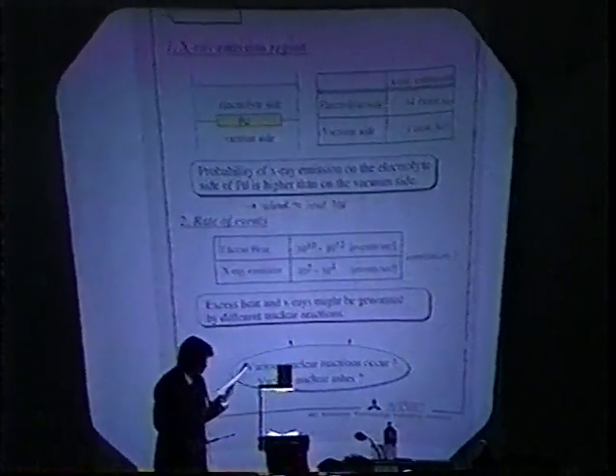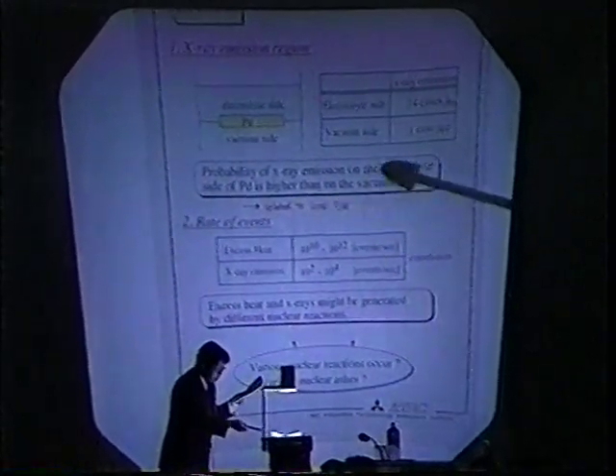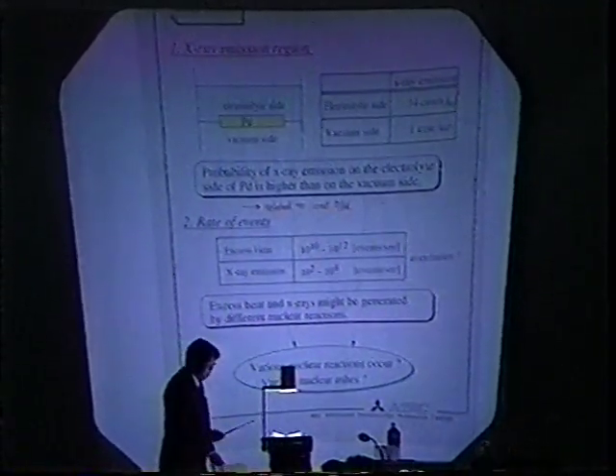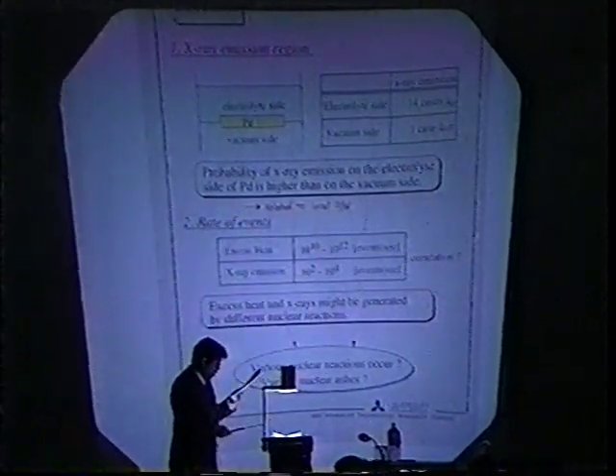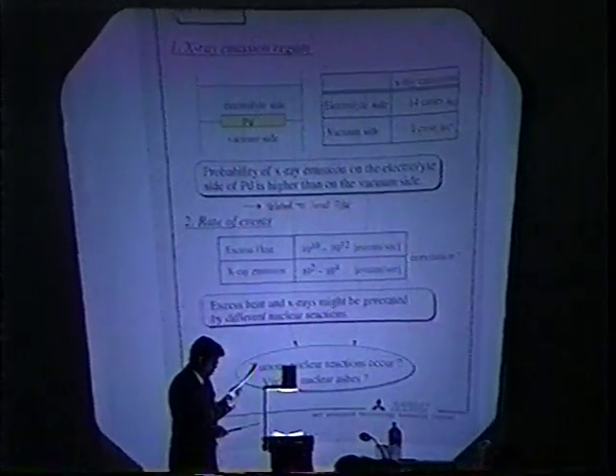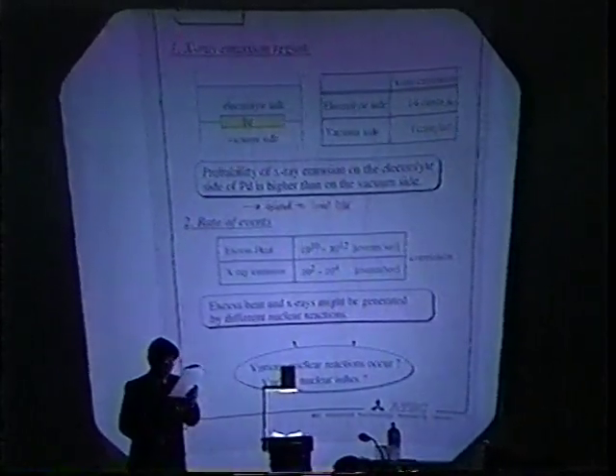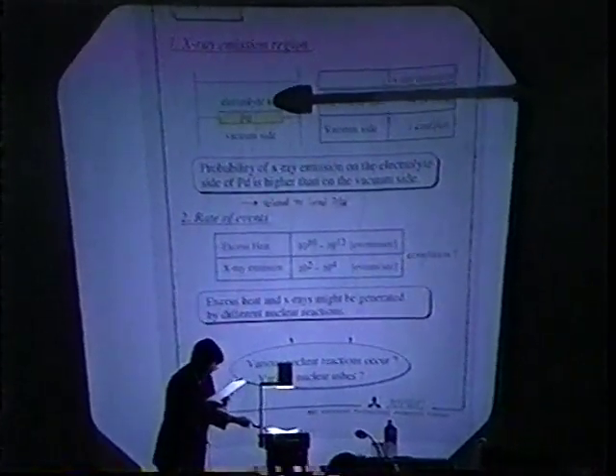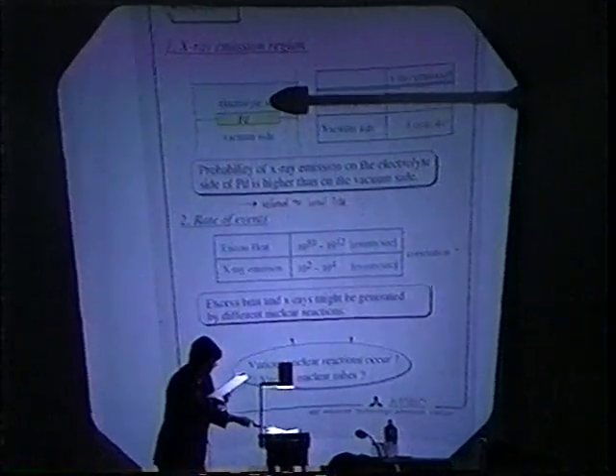And therefore, the probability of X-ray emission on the electrolyte side of PD is higher than on the vacuum side, and I suppose that the reason is related to the local D/PD ratio, since the local D/PD ratio is considered to be higher on the electrolyte side than on the vacuum side.